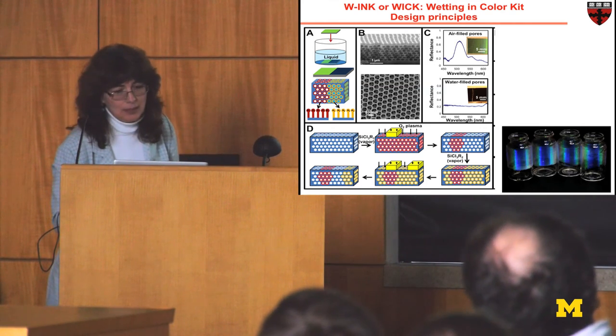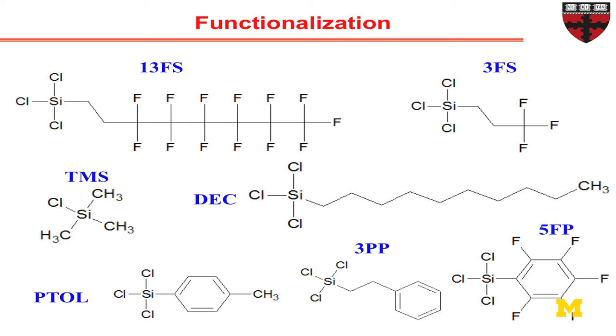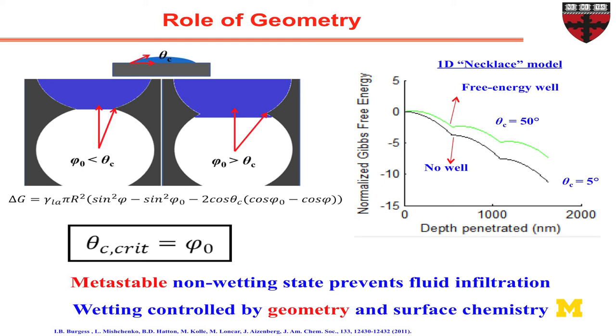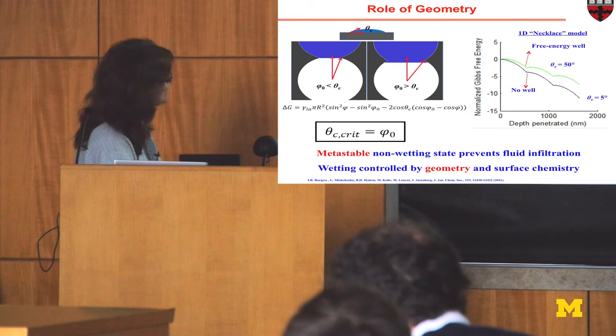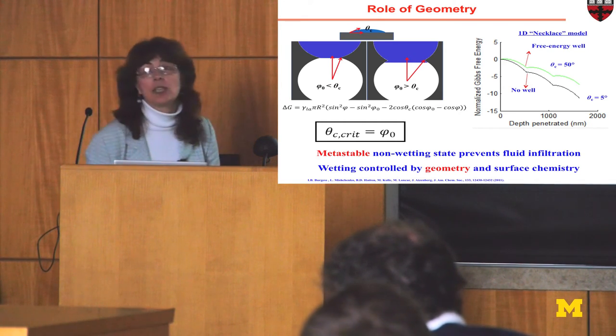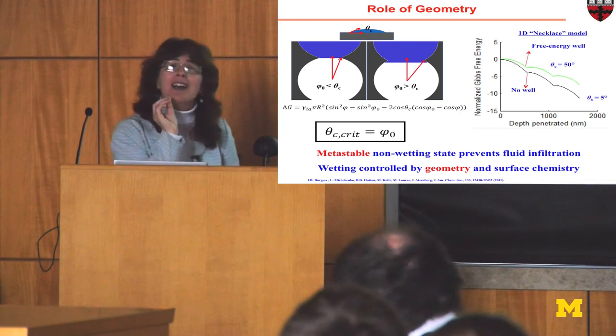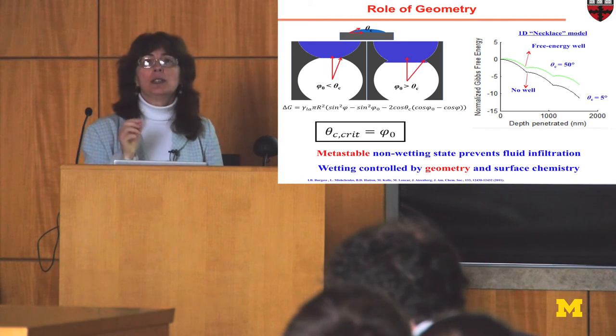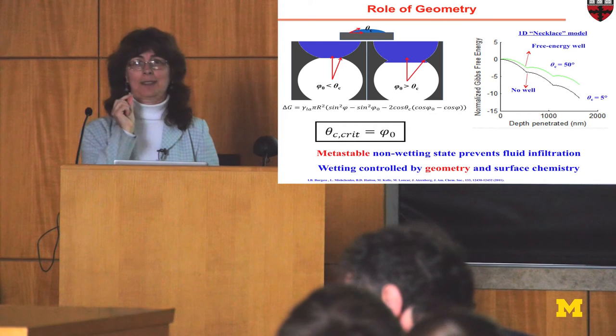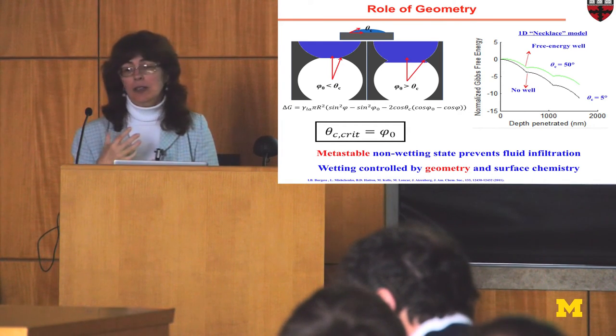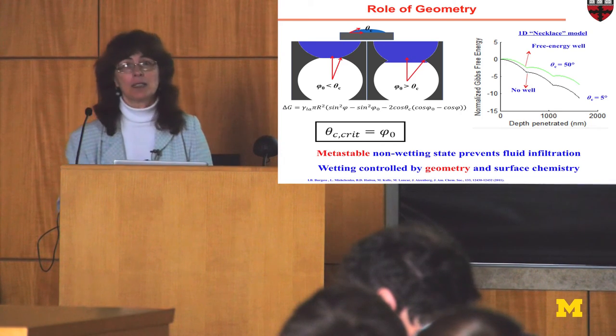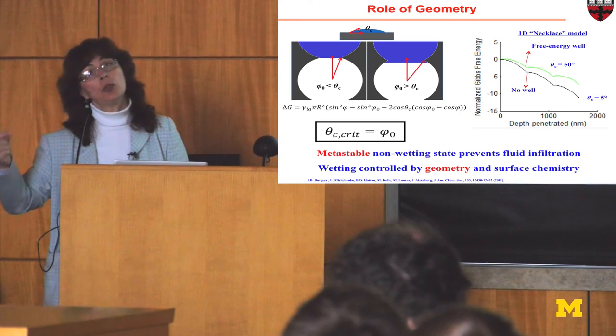And if we do that, and we use a variety of possibilities, there's a lot. But also remembering that it's not only chemistry, but the fact that I have an almost perfect colloidal structure. There's a liquid for the infiltration. It's not enough to wet the surface. It actually has to have a certain envelope, because to go from one pore to another pore it has to overcome that barrier. And then you can tell you all about it and how much energy it costs. So a combination of geometry and surface chemistry gives you the ability to create a highly sensitive surface that will give you up to 1% difference in concentration of one liquid in another liquid to be able to resolve it from the point of view of what it can or cannot wet.